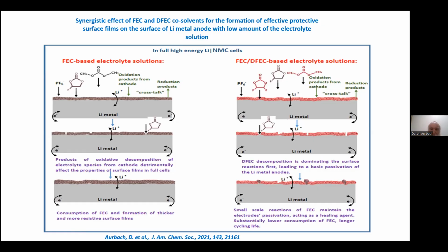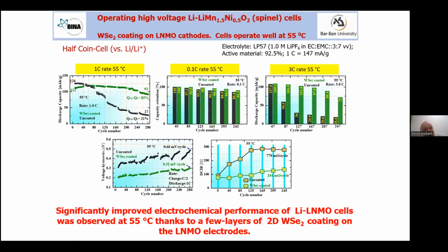So now we can go to more interesting materials, as we are happy with stabilization of the lithium side. Now we can go to 5-volt systems. So LNMO is a lithium nickel manganese oxide spinel. This is a 4.7 volt cathode material. And here, we need the buffer zone. We have to avoid dissolution of nickel and manganese into the electrolyte solution. So we need coating.